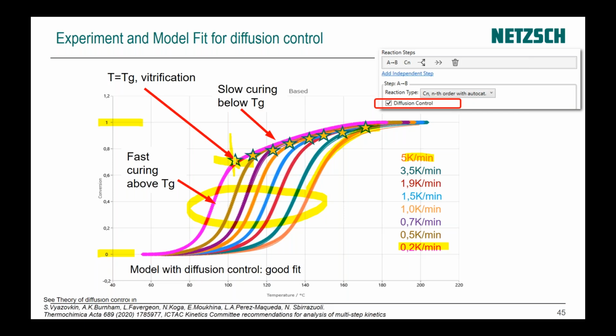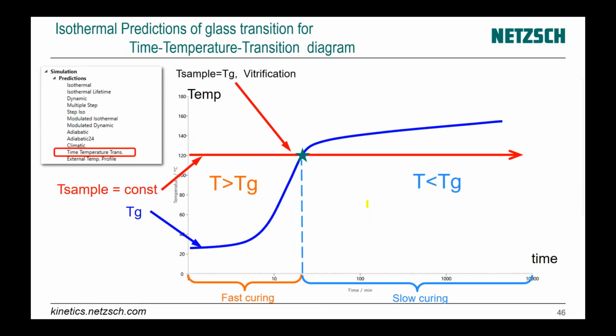This point, where the mechanism changes, is the point where the sample temperature crosses the glass transition temperature - here we have a vitrification point. The material changes its state from elastic state to glassy state, and then curing becomes very slow.